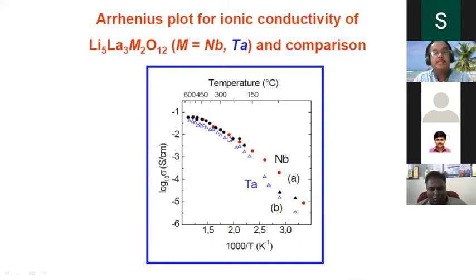But they made, instead of tantalum, they put niobium. They want to compare these two materials. Then niobium has the better conductivity compared to tantalum. Still, it's 10 power minus 6. So it may not be suitable for making a solid state battery, but the conductivity is quite good. Fortunately, this is an added class now in the family of the lithium ion conductors.